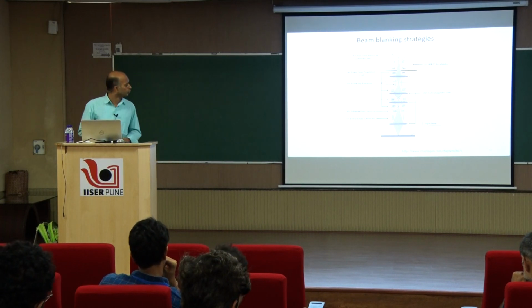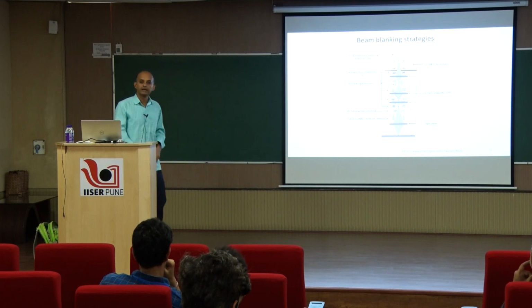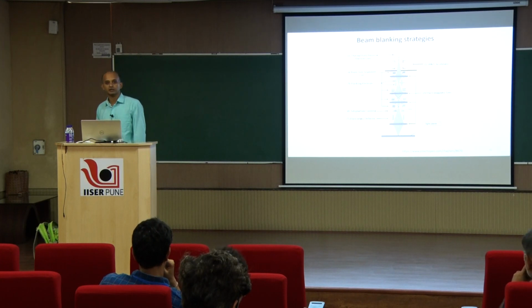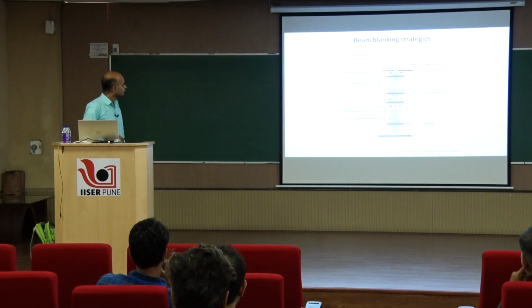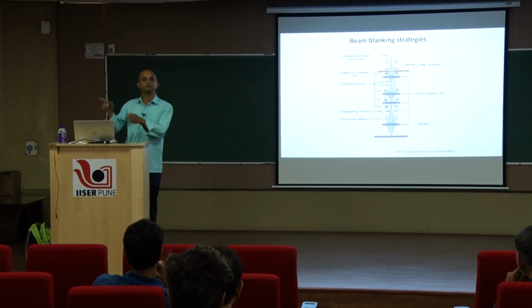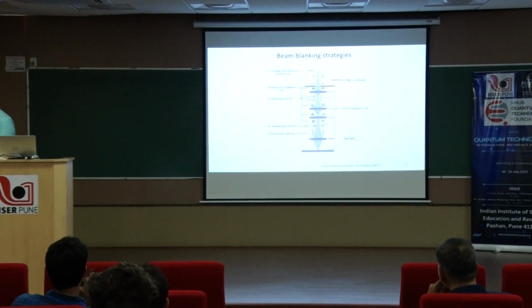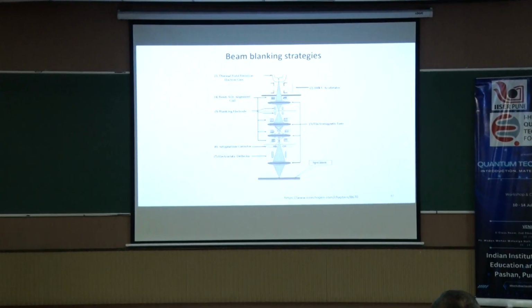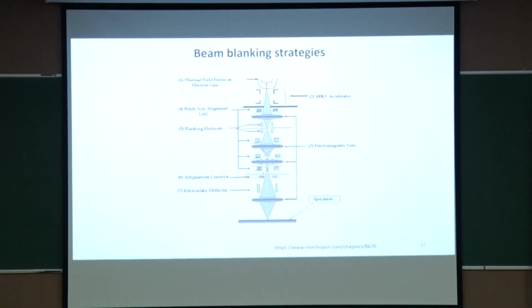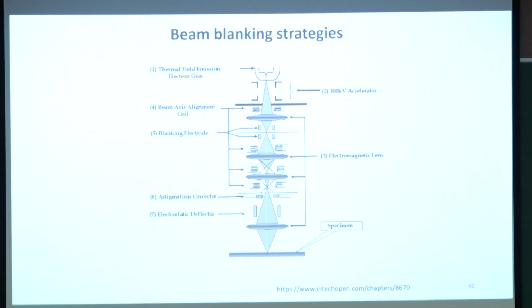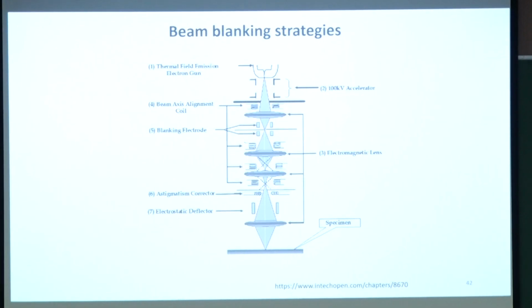In a conventional lab, everyone has an SEM, so what they do is install a beam blanking electrode. They buy it from Raith, which is much cheaper than anything else, and you can convert your conventional SEM into an E-beam writer. That is a great thing, especially for doing research on a low budget, but this is not the dedicated machine, because you can see that the accelerating voltage is 100 kV.